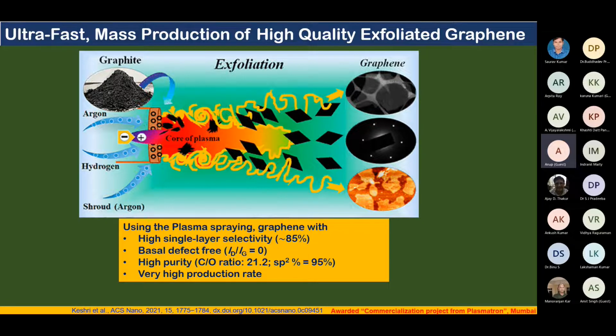We know that in graphite, between the layers there is a van der Waals force, and if we can somehow exfoliate the single layers from the graphite, then it will be very easy to make the powder through plasma spray. Because plasma can give high temperature, it can give thermal shock. Thermal shock means very high temperature, but the quenching rate is so high that my powder particle may not get oxidized. Once the bonds between the layers get weakened, we accelerate the powder towards the powder chamber, where it will completely disintegrate. This was our idea, and now let me show you how we proceeded and what we got.